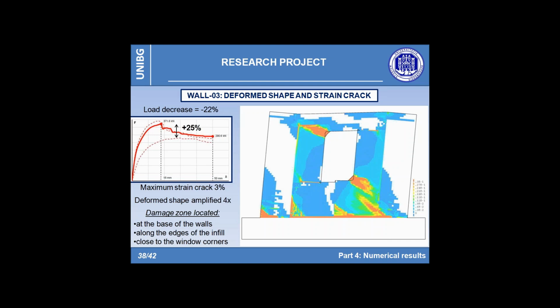The numerical model proved to be extremely accurate, being able to capture both the sliding mechanism that occurs between the two infill halves and the main damage. As also reported in the figure, the widest cracks develop from the corners of the window along the construction joints and between the infill and the walls. Contextually, the outer frame presents a crack pattern very similar to the one related to the first two walls.